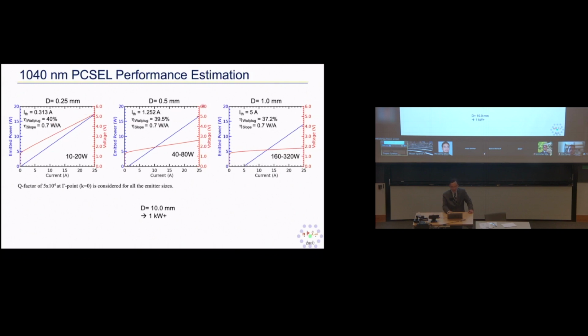For different sizes of the device, this aperture size D here is a lateral dimension, how big the laser is. Generally speaking, if you have a 250 micron aperture device, you get about 10, 20 watts. But if you want a 1 millimeter or 1,000 micron aperture, you can get a few hundred watts, in principle. And if you want a kilowatt, just make it larger, 10 millimeters, 1 centimeter size. So it can potentially scale to very large areas.